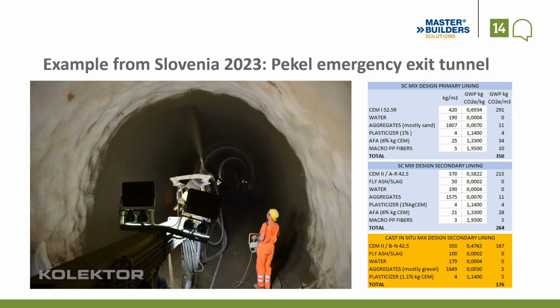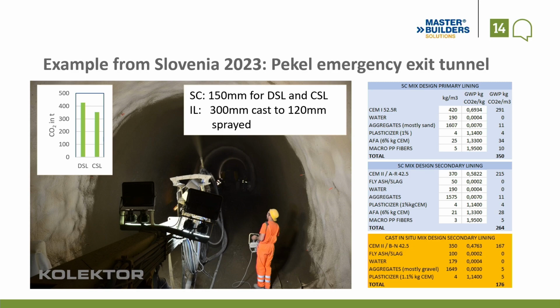And if you do the mathematics on that now, the spray concrete first lining was left with 150 millimeter. The inner lining was changed from the 300 cast to 120 spray applied. And the total reduction in this very short, small tunnel was 75, 80 tons CO2. You could say it's not so much, but at least a good start, and a good reference, and a good training. That's what I recommend to everybody. Give it a chance, try this, it works. If you do it right, it works.